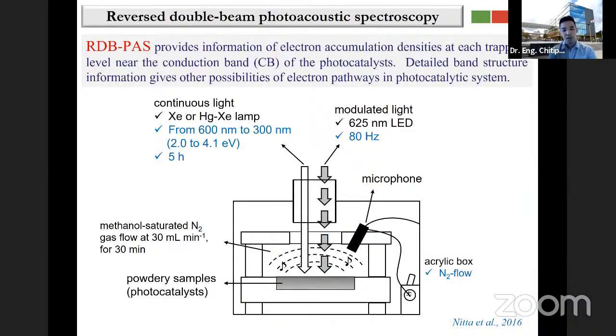Also, in this work, because we want to know about the generation of a new electronic state or new electron trap state level, we need to use a newer technique, reversed double-beam photoacoustic spectroscopy. This technique was developed by Professor Ohtani at Hokkaido University, and the result of this technique is called the ERDT pattern, or energy-resolved distribution of electron traps. The result of this technique can show you the electron accumulation density in each electronic state.